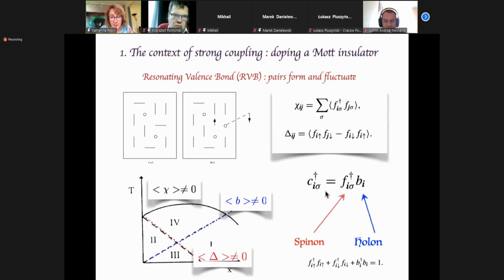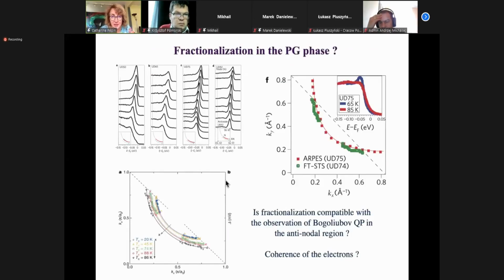So this type of theory was studied for many years. There was a point where I suppose it was difficult to get a job if you didn't go in this direction. Correlations are supposed to be extremely strong and fractionalize the electron into these elementary carriers of spinons and holons, charge and spin. I don't believe in it personally, for one reason. ARPES has seen, inside the superconducting phase, very beautiful Bogoliubov quasi-particles in the antinodal region. This antinodal region is supposed to be the pseudogap. And in a pseudogap, the electron is supposed to be fractionalized. But well, okay. Namely, this pseudogap is completely reconfined inside the superconducting phase. And we can see the Bogoliubov excitations over there, which imply that the quasi-particle, the electron at least, has its own integrity in order to form the Cooper pair.